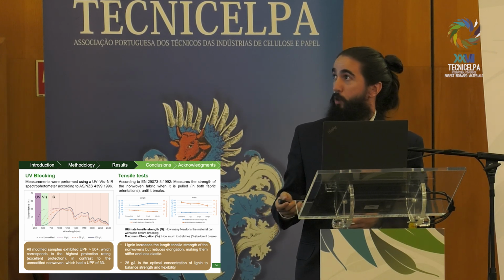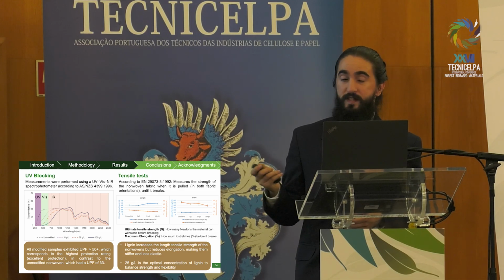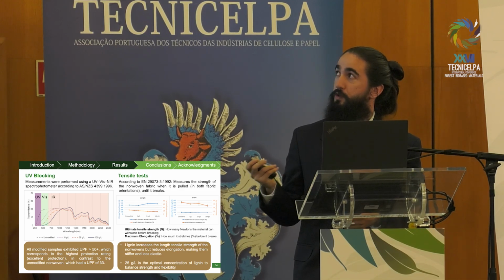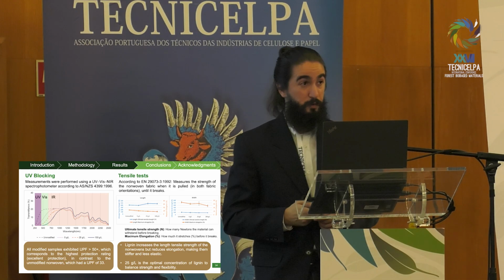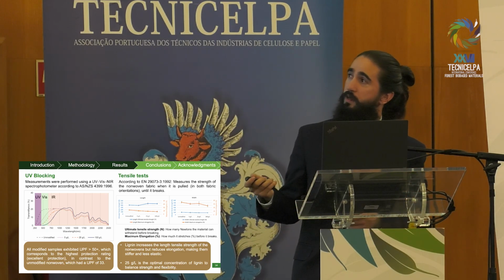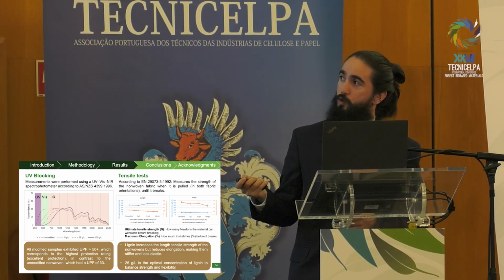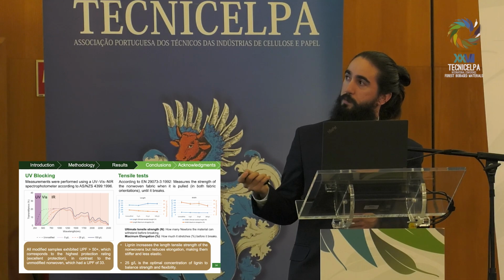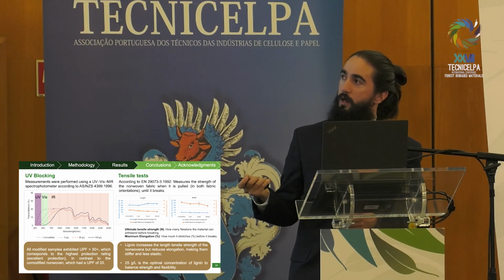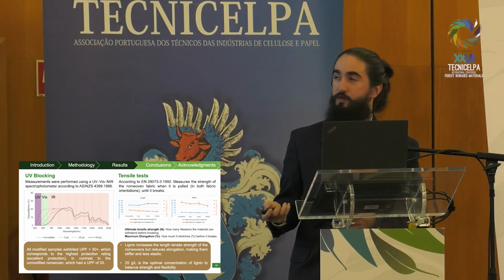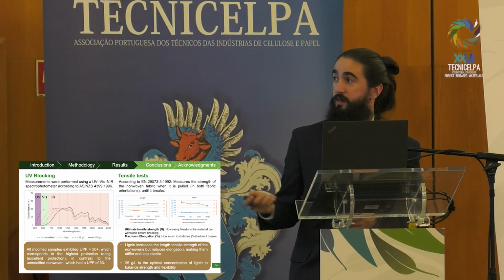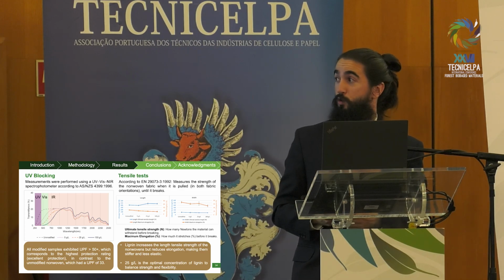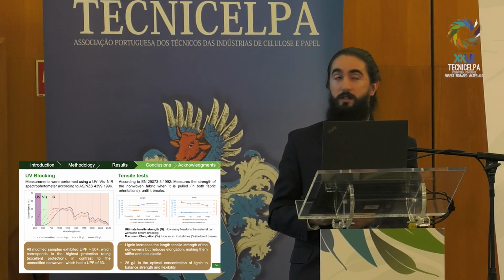Then for properties, in terms of UV blocking, we assess using the norm presented here, using a UV-Vis spectrophotometer. And as you can see here, in the transmittance graph, in the control group, it went almost up to 20%, but as we add more and more lignin, it reduced almost to 0, which clearly affects the ultraviolet protection value, which changed from 33 to 50 plus, which is considered excellent protection against UV.